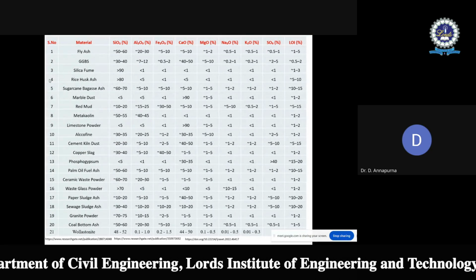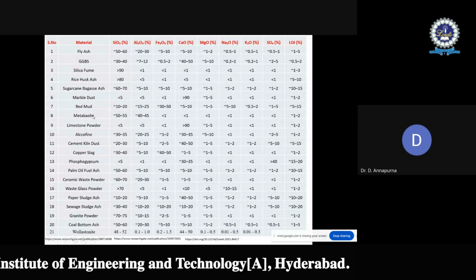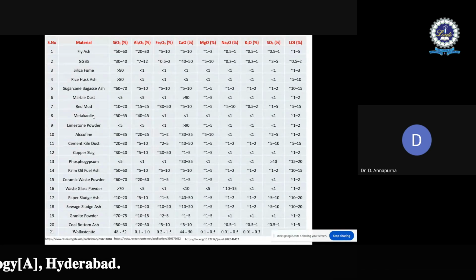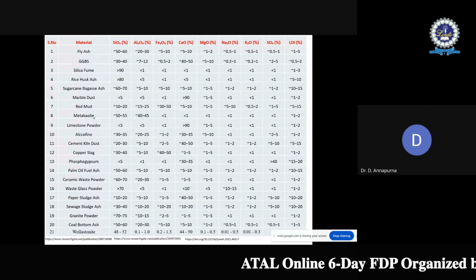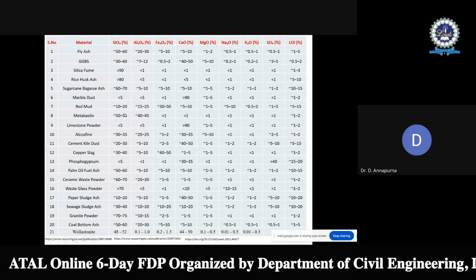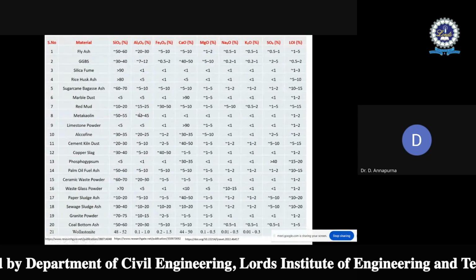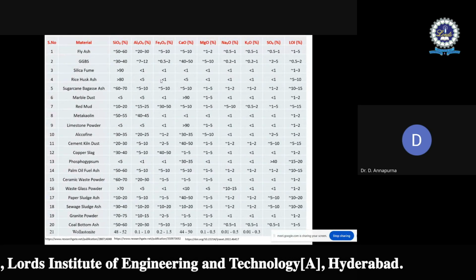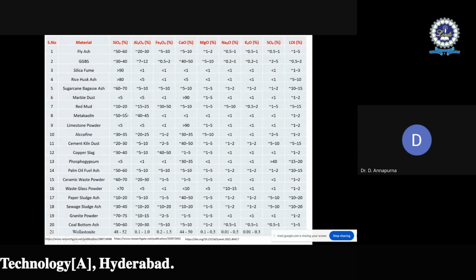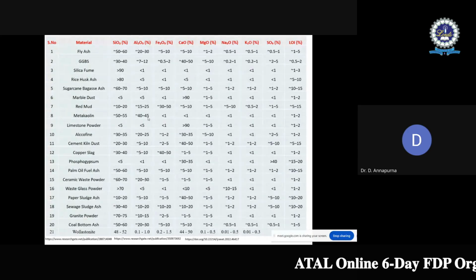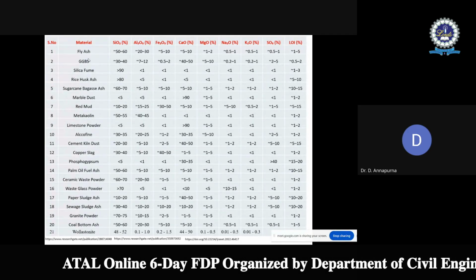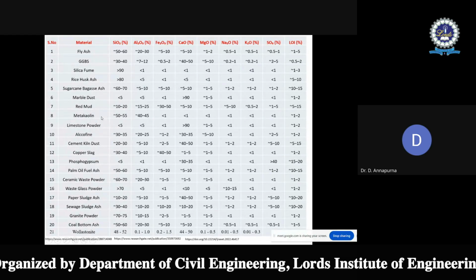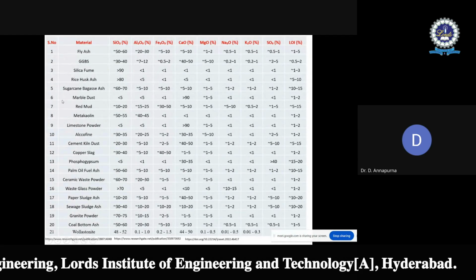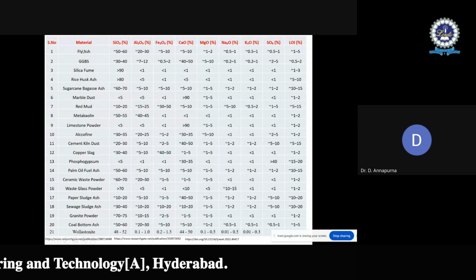Then the metakaolin. If we see the literature on geopolymer concrete, the early literature reveals that the initial geopolymer concrete preparation was done using metakaolin only, because metakaolin is proved to be the best source material for preparing geopolymer concrete, as it is equally rich in silica and alumina. Around 50 to 55% is silica content and alumina is 40 to 45%. So the initial research work progressed with this material, but because the cost of metakaolin is high, the research switched towards making use of cheap materials like fly ash, etc.